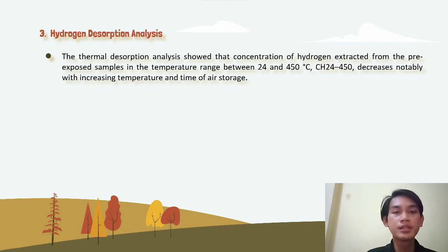3. Hydrogen desorption analysis. The thermal desorption analysis showed that the concentration of hydrogen extracted from the pre-exposed samples in the temperature range between 24 and 450 degrees Celsius, CH 24 to 450, decreased notably with increasing temperature and time of air storage.